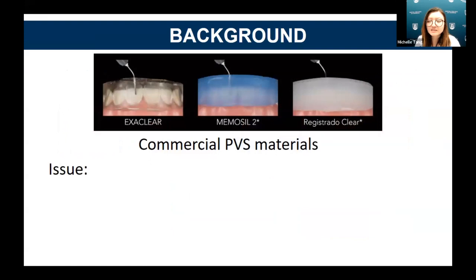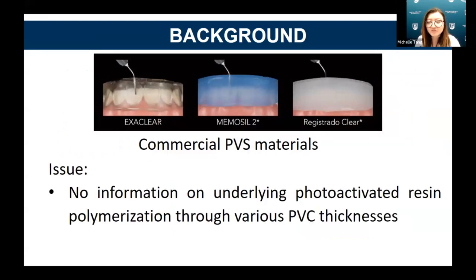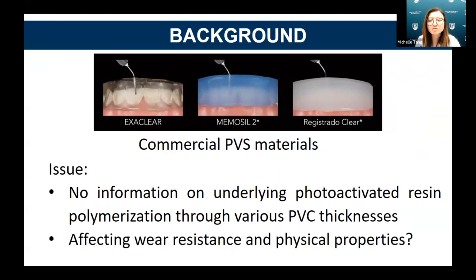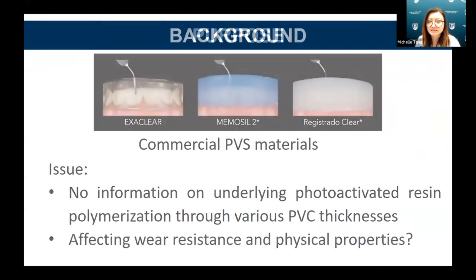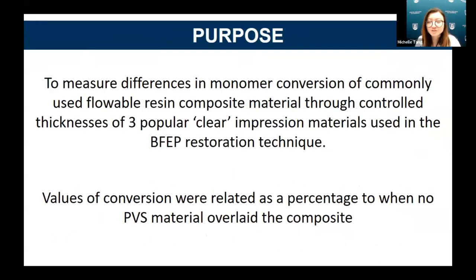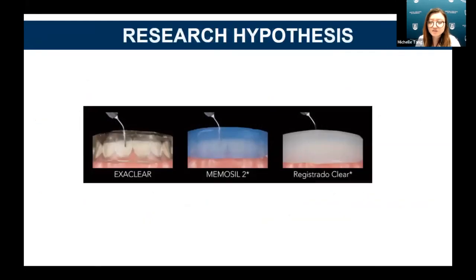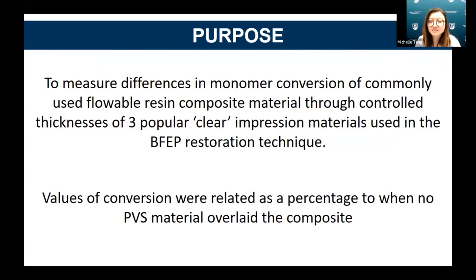Currently, there are available PVS impression materials marketed as clear for this technique. However, there has been no information revealing how well the underlying photopolymerized resin can cure through various material thicknesses. Incomplete cures could alter the physical properties of the material, leading to changes in wear resistance. Thus, the primary focus of our research was to directly assess the effects of PVS materials on composite curing by measuring the differences in monomer conversion of flowable composite through controlled thicknesses of 3 popular clear PVS impression materials used for this technique. Additionally, values for this monomer conversion were related as a percentage to when there was no PVS material overlying the composite within these groups.